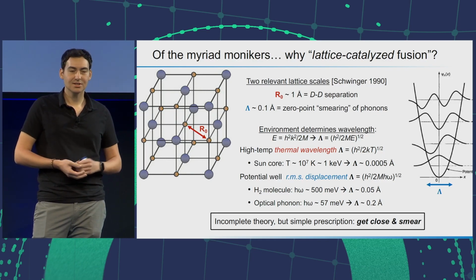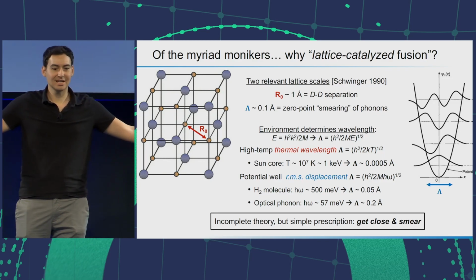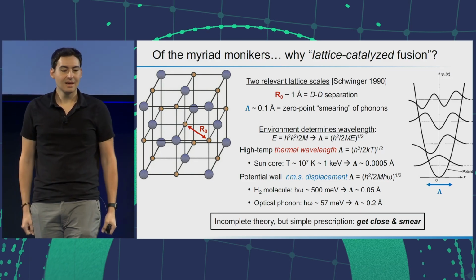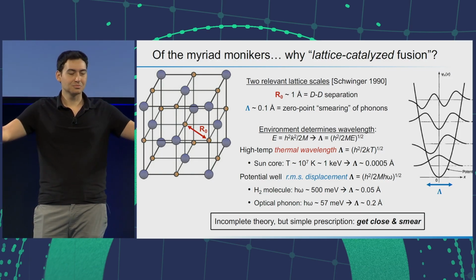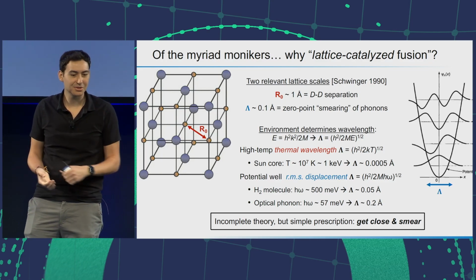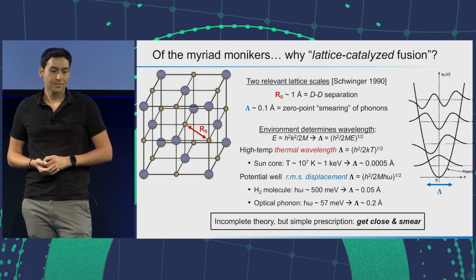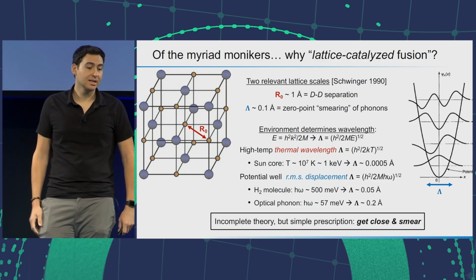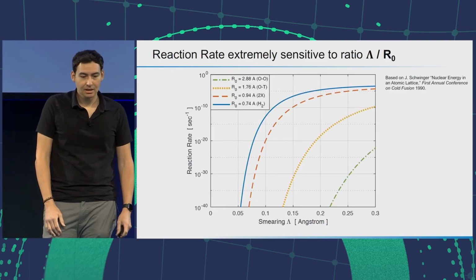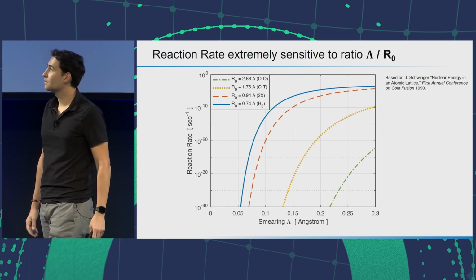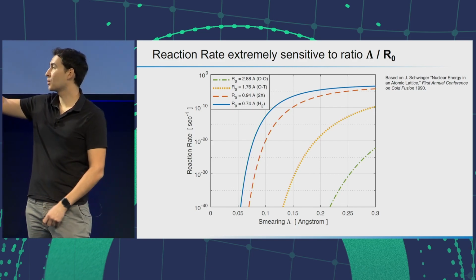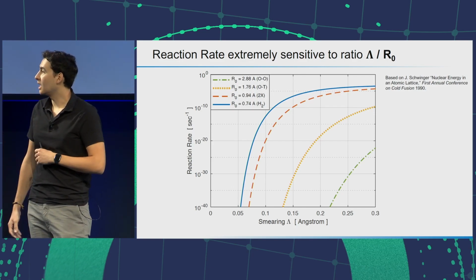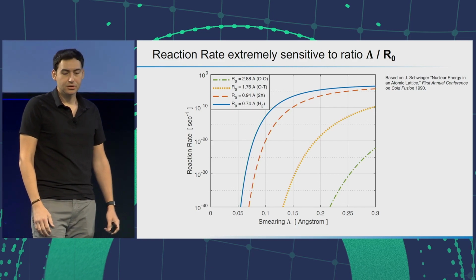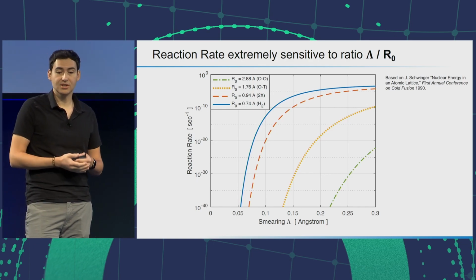We want to minimize R0, because we're talking about fusion at the end of the day. We do want things to overlap, and increase smearing. So get close and smear is the simplest way of putting it to maximize the probability of a reaction in this system. And so to be a bit more quantitative, here's an example of a numerical calculation. So taking Schwinger's result and just extending it for different parameters. And you'll notice a strong sensitivity to this ratio, lambda over r.